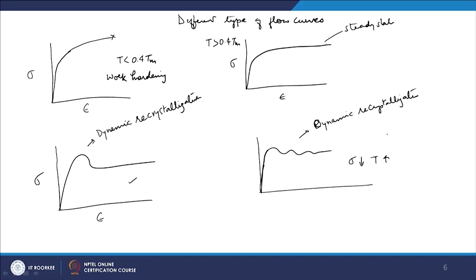Now one interesting thing you can do is, as I was showing earlier, that the effect of strain rate and temperature is entirely different on the stress. If you remember, if I increase the strain rate, or decrease the temperature, my stress will increase. And if I do it the other way around, there is an almost opposite effect of strain rate and temperature on stress, and we have given you two different equations for that.